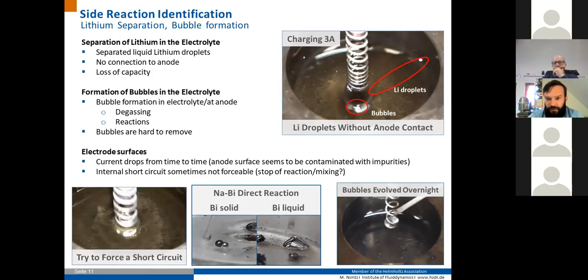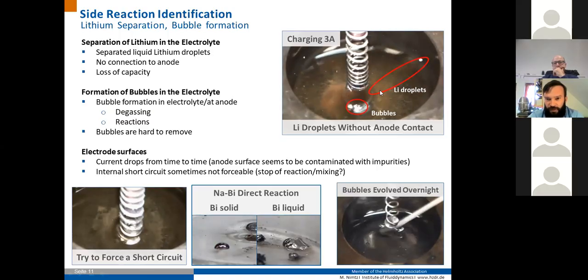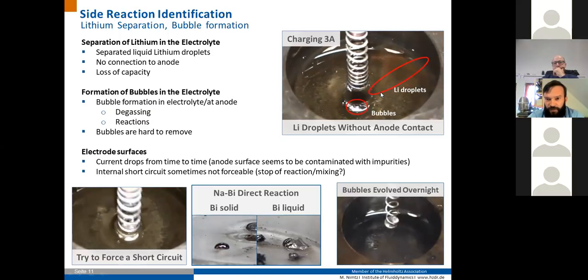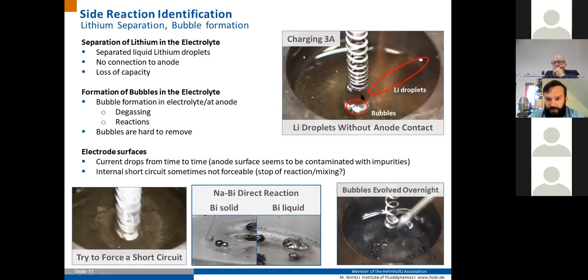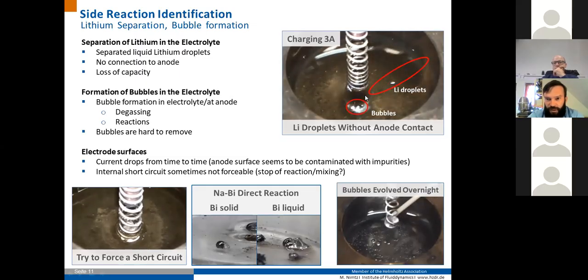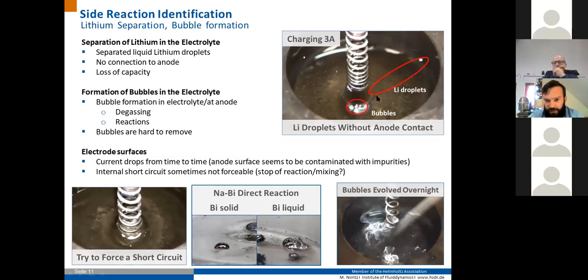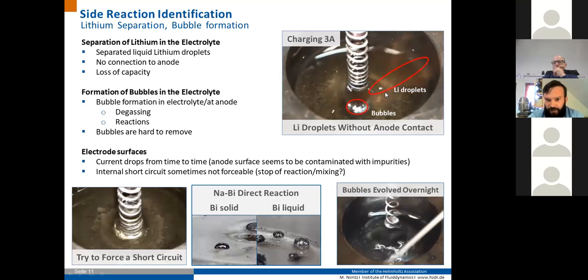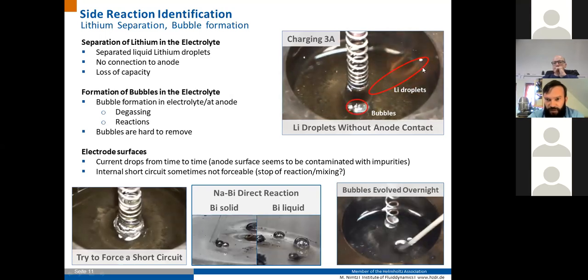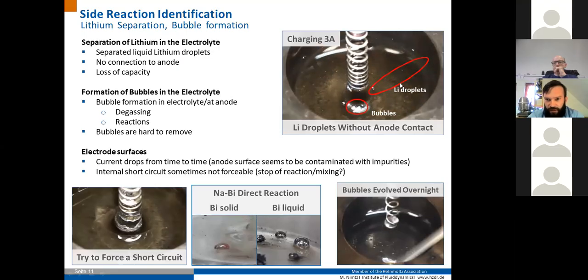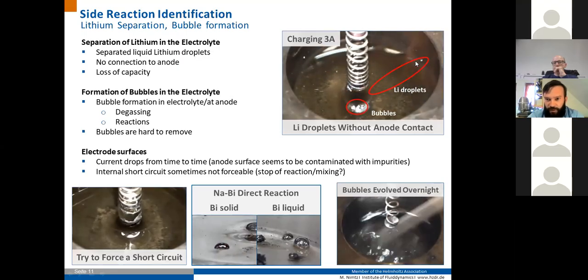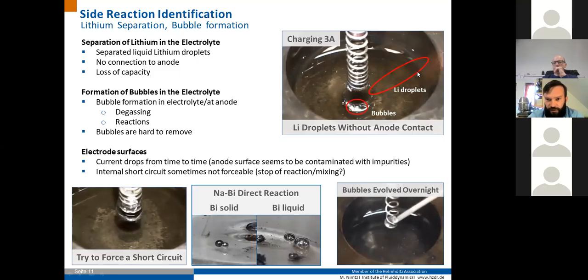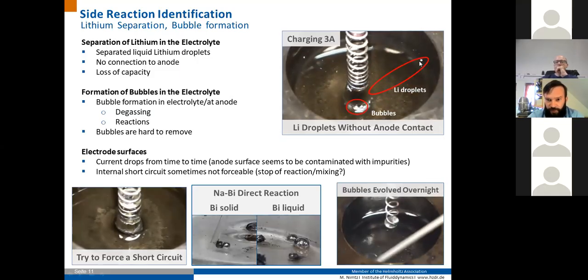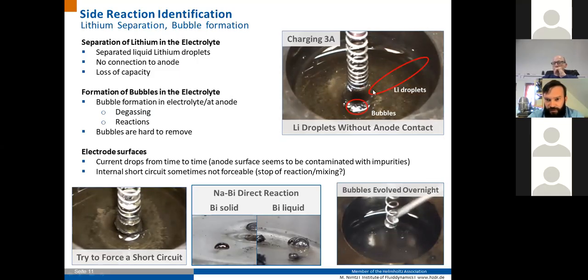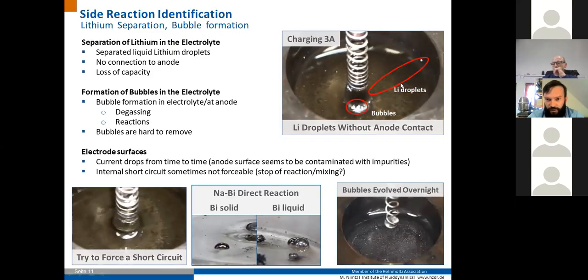And the problem here is, as these lithium droplets form and they float in the electrolyte, if these droplets do not stick to the surface of the electrode, you lose first capacity, and second, you will contaminate your crucible, and this could be a potential short circuit starting point if you have conducting lithium droplets here.